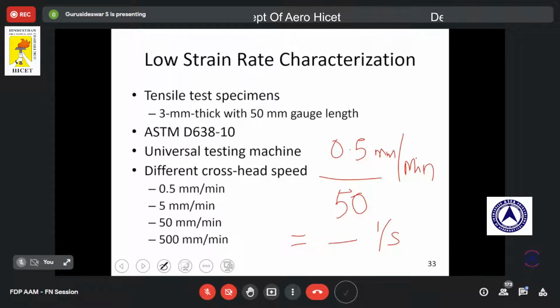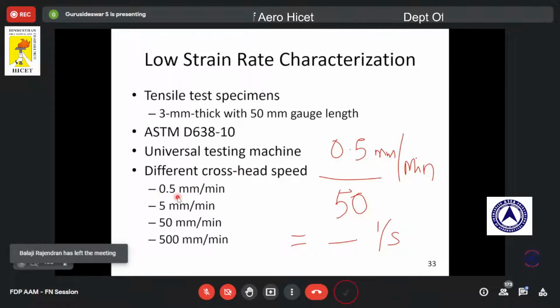So 0.5 mm per minute can be converted into mm per second, and then this value has to be divided by the gauge length. Then I will get the strain rate. To get different strain rates, we need to have different velocities, right? We need to have different cross speeds. So we used an Instron machine. In that machine we can set the speed, and it varies from 0.5 to 1000 mm per minute.